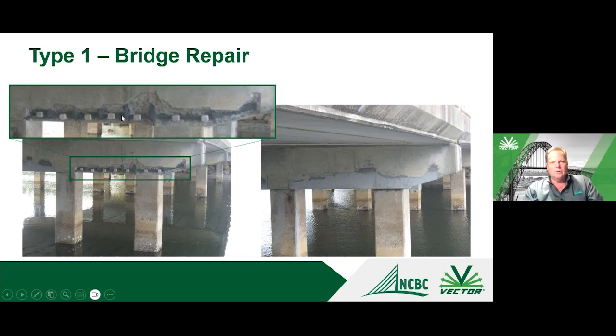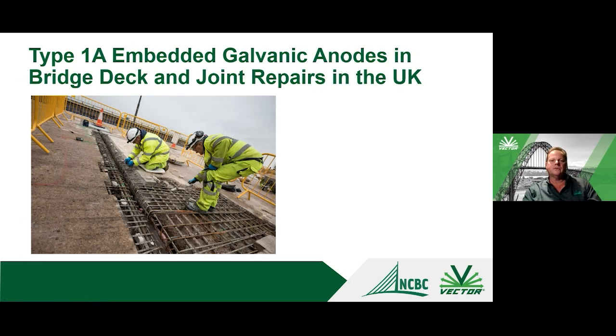And so this is a couple pictures of this type of application. This is showing a concrete repair on the bottom of the beam, and the subsequent repair. And it's just important to point out that these discrete embedded anodes are really just designed to make that repair in the surrounding area last longer. If you're going to do the repairs, it's a tool that you can use to make the repair more durable, but they're not really having any substantial impact on other areas of the structure. It's just type 1, just to make the repairs last longer.